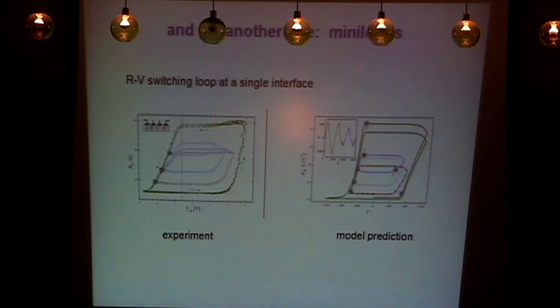Things do move through the interfaces, but the way to think of this W of the memristors is just the total quantity of vacancies that you put into the interface. So this you can take out. So the proportion of vacancies that you put there. Within the interface, the simplicity of the model tells you that anywhere you put them in the interface, they contribute the same, and anywhere you put them in the valve, they contribute the same. So the only changes you get are from going from the interface into the valve or from the valve. So the ratio between the two will be this W that is associated with the physical position in the model. So Stan, would you like to make a comment?